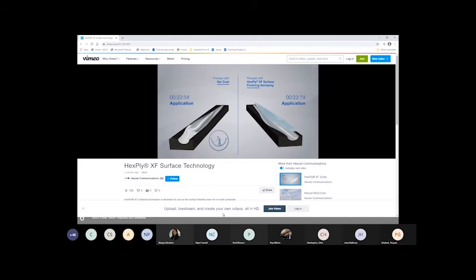And on the right, you've got what we call Hexcel XF technology, which is a fiber reinforced product being laid down into the tool. So in about the same time or less time, you've got both tools prepared for your composite structure to go in. But the gel coat now has to be gelled, which involves heating the tool up. And there's a lot of thermal inertia there and a lot of energy to do that. And then cooling back down again before you can start laying up your prepreg or your dry fiber on top of it. Whereas with XF technology, you're ready to start that composite layup straight away.